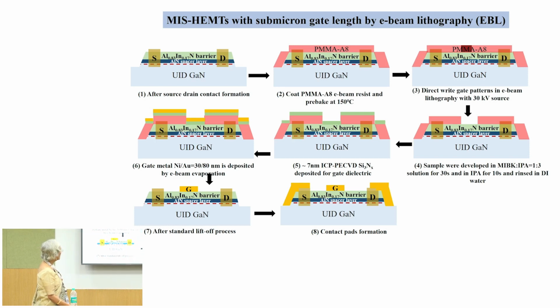And here we have used PECVD silicon nitride, about 7 nanometer of PECVD silicon nitride as gate dielectric, and the gate metal is nickel gold, and after the standard lift off process, you can see here the gate is sitting on this very thin silicon nitride layer, and finally we have the actual device. So, this is the MIS HEMT fabrication, where the gate dielectric is silicon nitride.